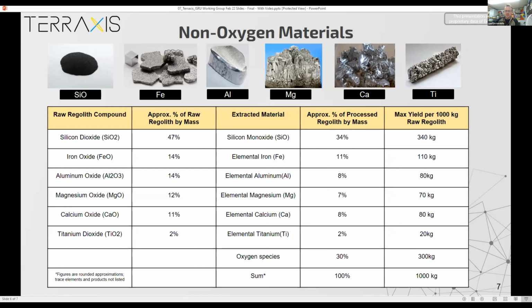So what do we generate? Unlike some other processes which are focused on a very specific kind of output, just as a matter of course of operating at the temperatures and pressures that we are aiming for oxygen generation, we're going to end up with these resultant yields. The primary non-oxygen product that we would receive is actually silicon monoxide, which I am interested in learning from the demand side guys talking later today, if there's any particular interest in it. I think we see it a bit more as a slag, a byproduct that is less useful than some of the other products, where the next most prevalent would be elemental iron, which could be used in all sorts of applications, as well as elemental aluminum, elemental magnesium, calcium, and then a tiny bit of titanium and other small trace products.